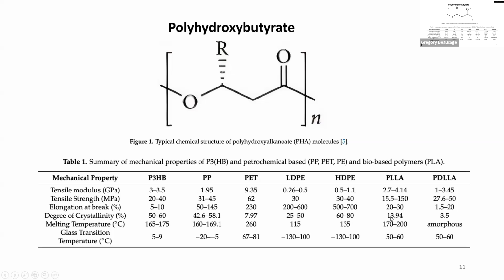So anyway, depending on how you make it, right? It's like PET, they say it's crystalline, but a water bottle is amorphous because you quench it fast enough; there's a kinetics issue with the crystallization, so it can't crystallize in time. It's got a high melting point, and the maximum crystallization temperature is like 50 degrees below that, so 210 C. You never reach that under normal conditions unless you put a solvent into it, and it'll crystallize right away. So there are different issues involved with these operating temperatures.